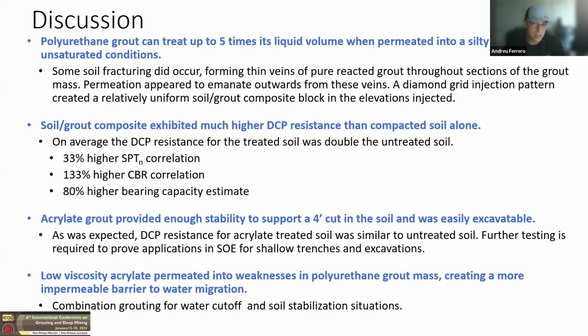The soil grout composite exhibited a much higher DCP resistance than the compacted soil alone: 33% higher SPTN correlation, 133% higher CBR correlation, and 80% higher bearing capacity estimates. The acrylate grout provided enough stability to support a 4-foot cut in the soil and was easily excavatable. As we discussed, we didn't expect the acrylate to increase the penetration resistance, but we do see the value in support of excavation for shallow trenches and excavations. This is a product that's used in underpinning, for example, to stabilize soils while contractors are excavating underneath footings so that the soil around them doesn't collapse in on them.